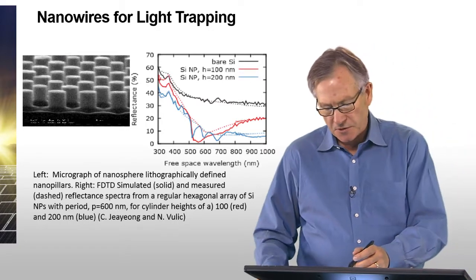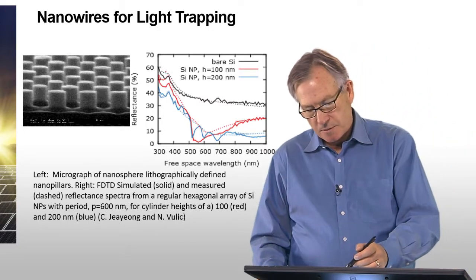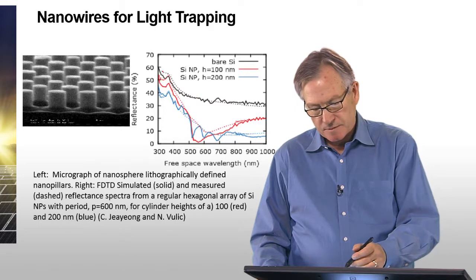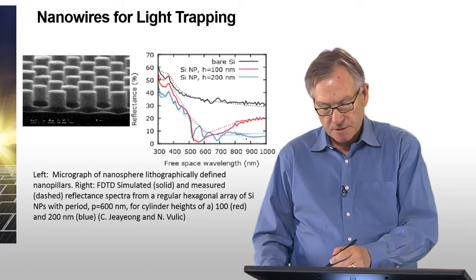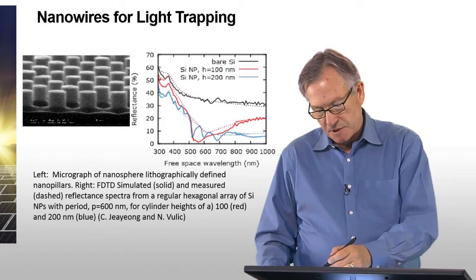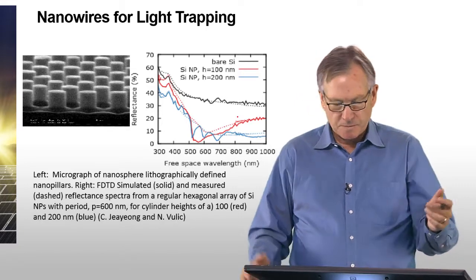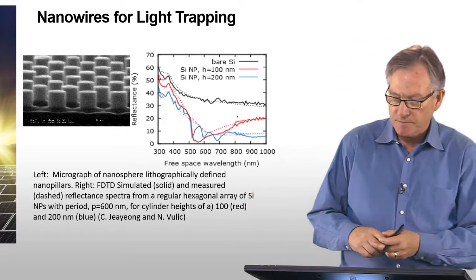And so what's shown here is measured reflectance from bare silicon versus nanostructured silicon. As you can see, there's a dip in the reflectance that goes through a minimum, so it basically acts like an anti-reflection coating.